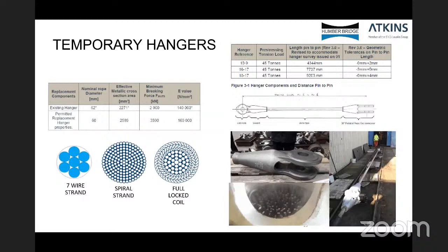this gives you some of the details around the temporary hanger arrangement. There were various options, but what was critical for the design of the temporary hangers is that the hanger creep and elongation over its in-service life didn't cause a significant change in the load pattern of the bridge. If we installed a hanger that hadn't been correctly shaken out, with correct frequency analysis and loading of the new cable, then that would cause a redistribution of loading throughout the adjacent hangers. And so to avoid that, the best hangers that we could find were fully locked coil hangers that were adequately loaded. For that reason, we were replacing the existing spiral strand hangers with a fully locked coil hanger.